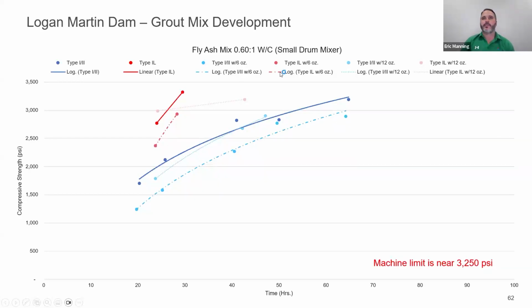One thing we noticed is that the Type IL does gain strength a little faster, but it tends to have slightly less strength than the Type I/II. Some of that may be attributed to the first batches that came out of the local cement plant. I think they had a little bit of quality control challenges early on in their Type IL deployment. According to our admixture rep, they were experiencing a little bit higher sodium carbonate levels in their Type IL cement, which acts as an accelerant.